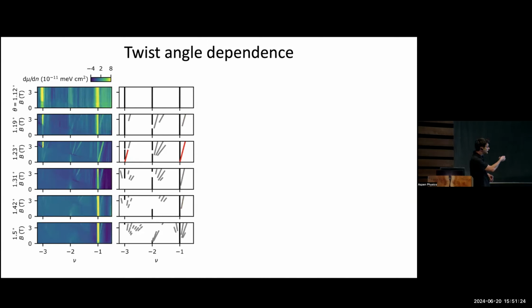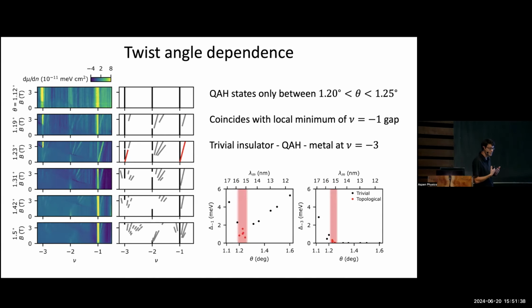If we increase twist angle, even up to 1.31 degrees, again, you can see at nu equals 1, the state is vertical down to 0 magnetic field. So we're changing the nature of the topology. There is basically a topological transition. You go from a trivial insulator at nu equals 1 to a topological insulator in a very, very narrow window between 1.2 and 1.25 degrees, back to some sort of trivial insulating ground state. So twist angle tunes dramatically the behavior of the system, and similarly for the state at nu equals 3, it's really only topological in a very narrow window.